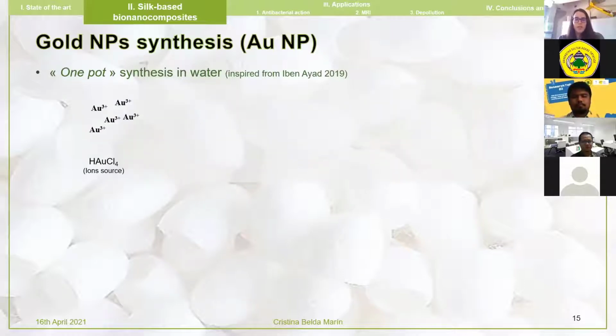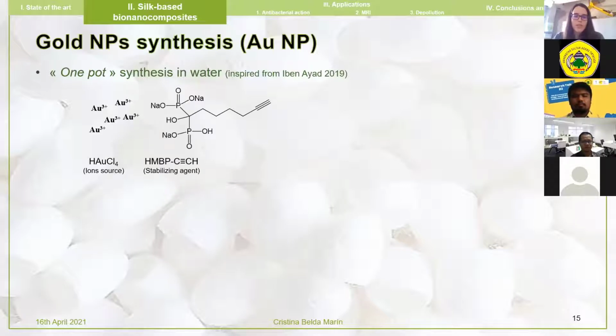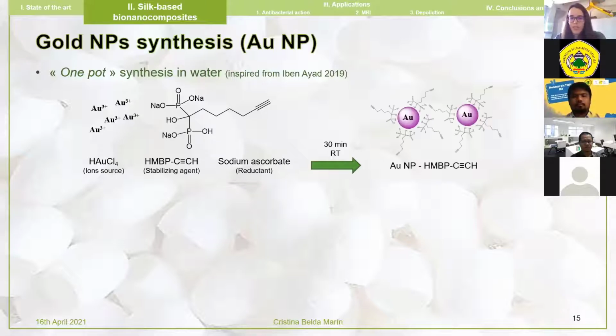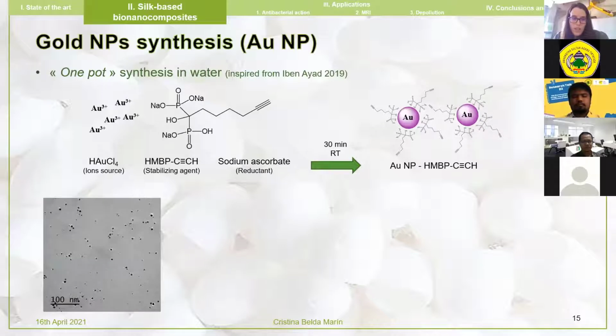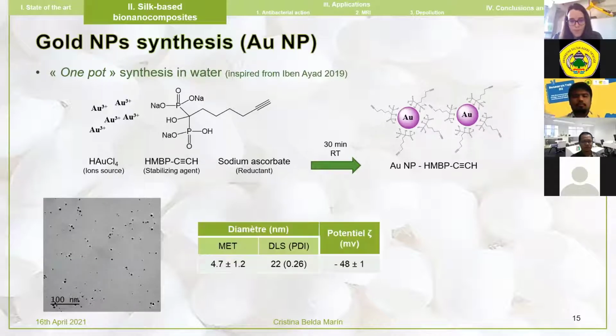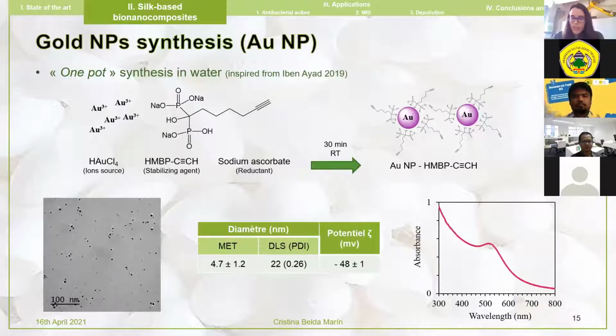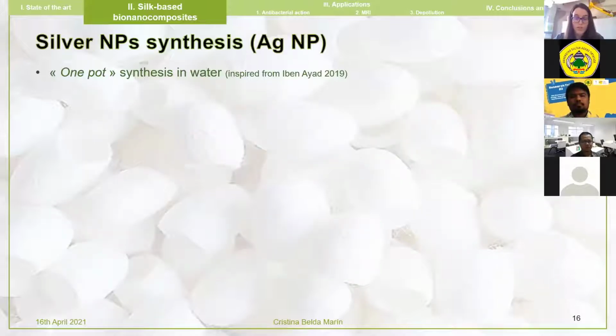So for gold nanoparticles, the idea was to take gold ions and place them in the presence of our stabilizing agent and our reductant, then 30 minutes at room temperature under agitation allows the formation of gold nanoparticles. And we have studied these nanoparticles by transmission electron microscopy. You see a diameter of 4.7 nanometers. More important, we have also shown by spectrophotometry that we have the well-known absorbance around 520 nanometers, that's known for gold nanoparticles.